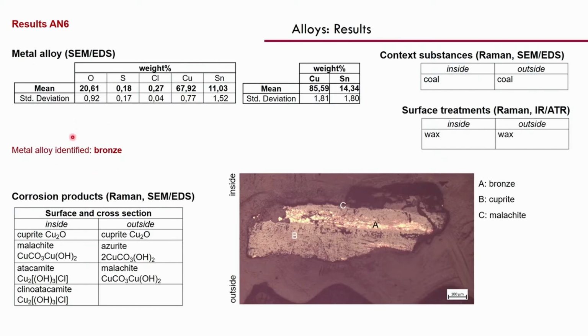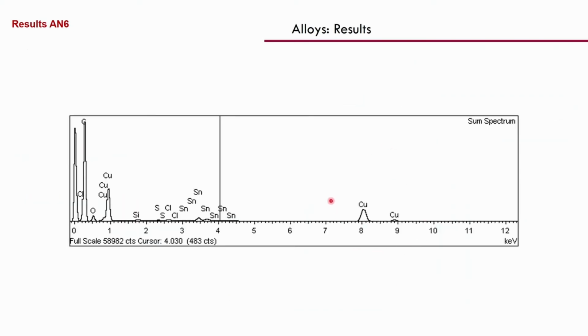Another cross section was very interesting. In this case, we analyzed the bronze, and you see in the center of the cross section the real bronze, so the metallic part of the alloy, the original alloy. And this was very interesting because we could see, even in this case, a wax as protective of the material, but you see that we could analyze exactly the composition of copper and tin in the alloy.